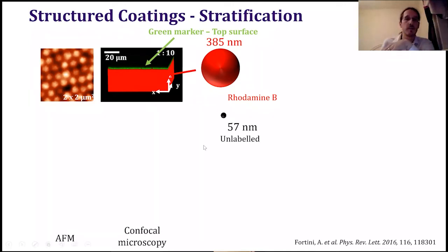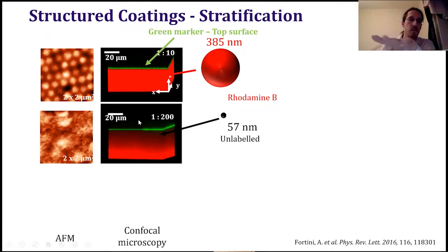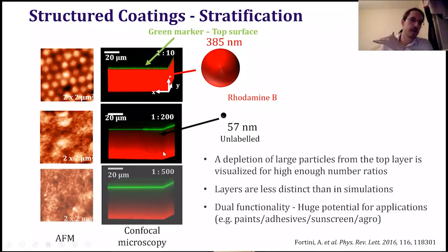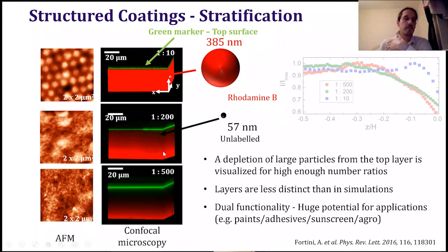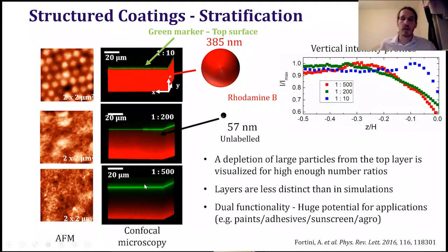So if we increase the amount of small particles, then we can see that the top surface changes. We don't see the large particles anymore. We see just the small ones. So we have the small ones dominating. And then when we look at the inside, the architecture inside the coating, we see that at the top we have small particles, because we see this black area here from the unlabeled small particles. And if we include even more small particles, this area becomes thicker and we still don't see any large ones at the top. So this was the experimental demonstration of how this stratification happened.